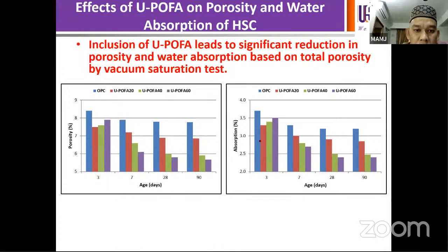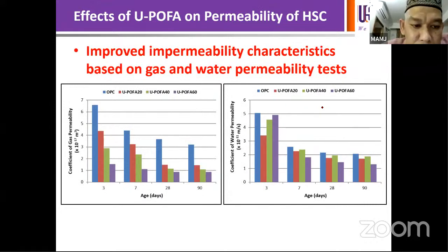All right. So in terms of porosity and water absorption, here in the case of palm oil fuel ash concrete, we can see the inclusion of this material leads to significant reduction in porosity and water absorption based on total porosity by vacuum saturation test. So here is a good point in terms of potential durability performance of the resulting concrete later on when we expose it to an aggressive environment, for example, because the concrete has lower porosity, fewer pores, and the penetration of aggressive agents from the potentially aggressive environment could be restricted better in comparison to 100% Portland cement concrete.